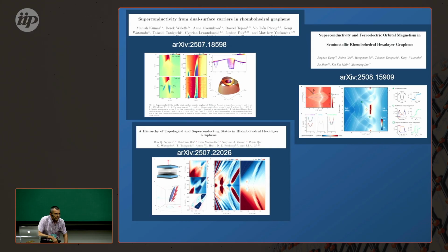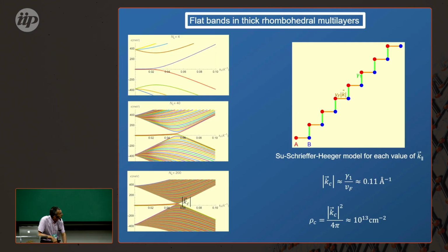And these are even more recent experiments confirming superconductivity in rhombohedral multilayers with different number of layers. And now the question arises, how many layers you need before the bulk bands swamp completely these interesting non-trivial phase diagrams and dominate, and you lose superconductivity.